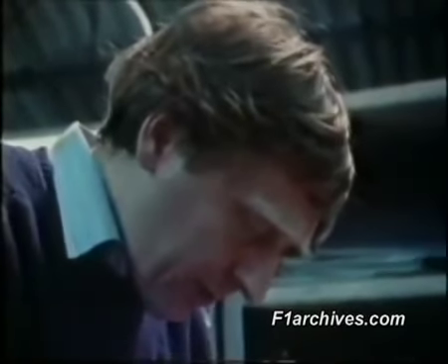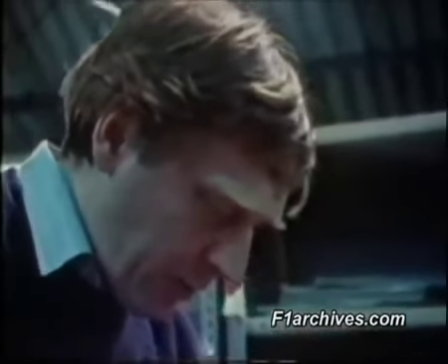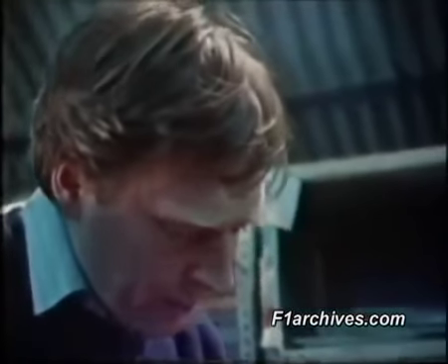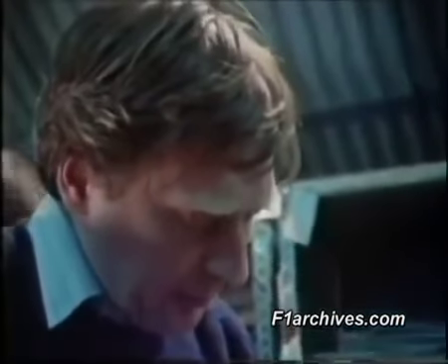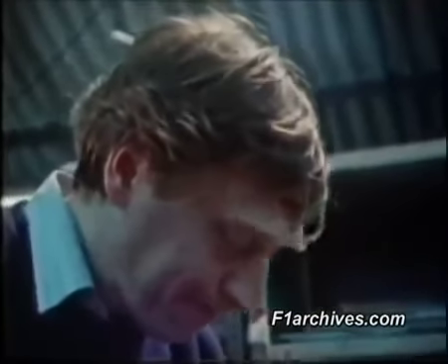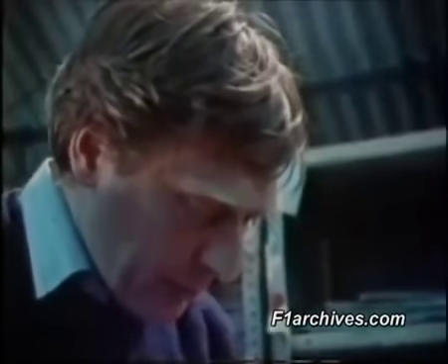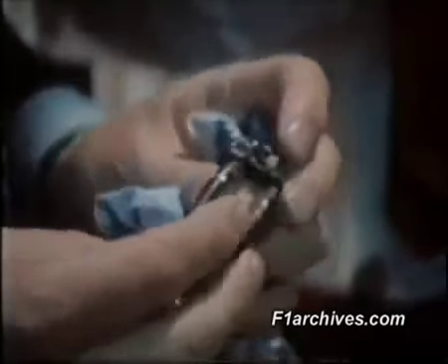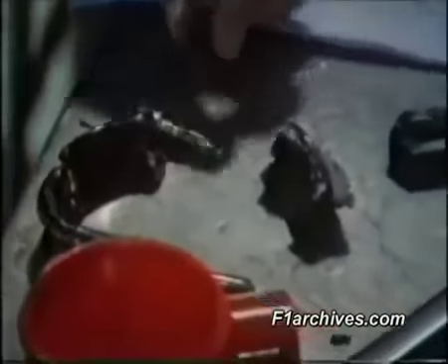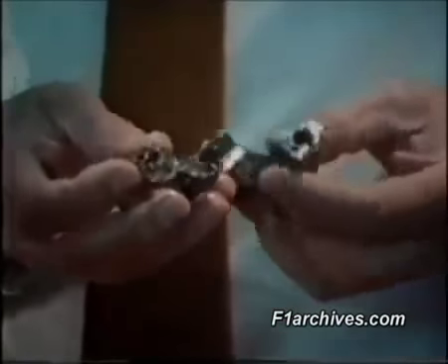The problem is there isn't as much heat as I think you normally see when you just lose a bearing. It's only come up about this far now. It normally tends to get a bit hotter. It may be that a bolt broke first. Excessive heat due to lubrication failure makes steel turn blue. Just hammered its way out through the edge. With no obvious discoloration, the search for the cause moves away from lubrication failure to metal fatigue.